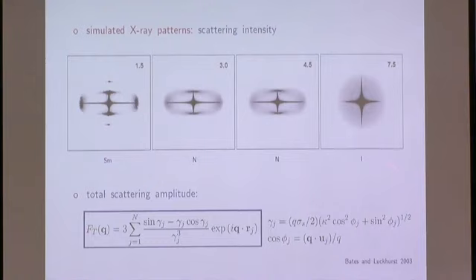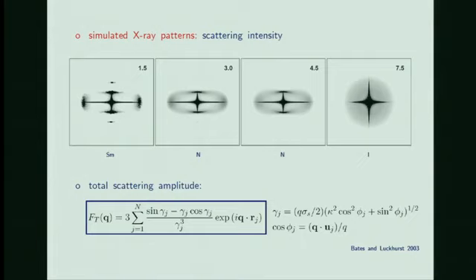First of all, you have to ignore this central cross here, because this is just a finite size effect. In our case, the director was directed vertically, and we have nice peaks here, and so on. These correspond to the correlations along the nematic director. But we also have lateral correlations, and these are visible here as these lateral arcs.